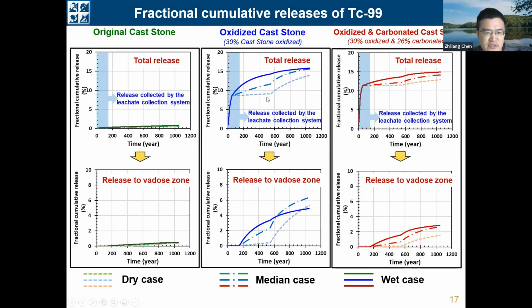So in each figure, you can see 3 different lines indicating the modeling results for the dry case, medium case, and wet case. If we take a look at the total release from the original Cast Stone after 1,050 years, we can see that the total release is less than 1%, which indicates good retention ability of the Cast Stone for the technetium. But we will also notice that after the oxidation or the carbonation of the Cast Stone, the release rate has been dramatically increased.